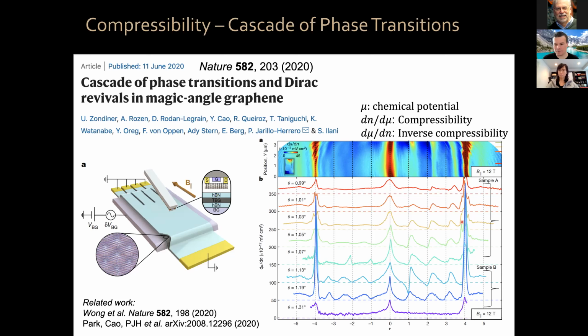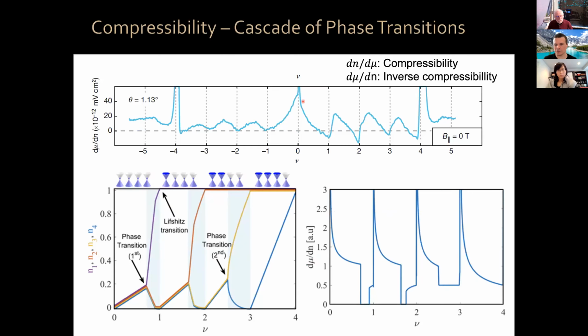Now what we saw is that if you look at a sample and you look at regions with different twist angles, around the magic angle, 1.1 degrees and nearby, there is this sawtooth behavior in the inverse compressibility where some feature appears at each integer, okay? Let me zoom in on one of these here. So you see this sawtooth behavior appears near each integer, okay?